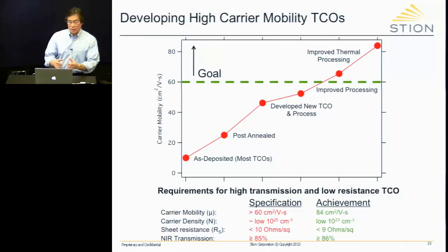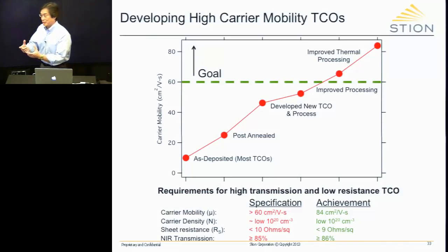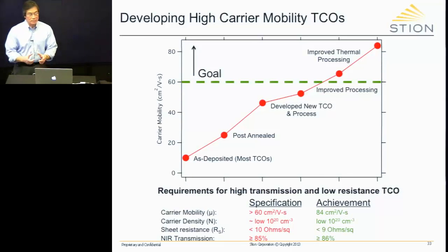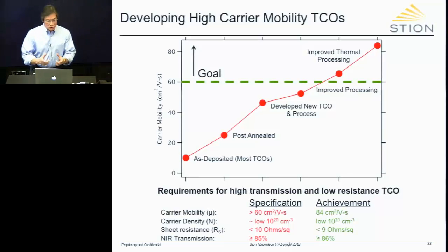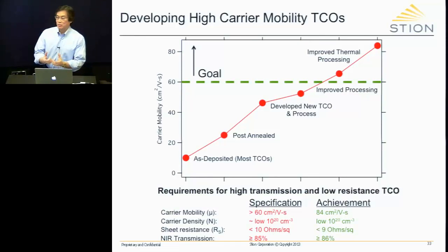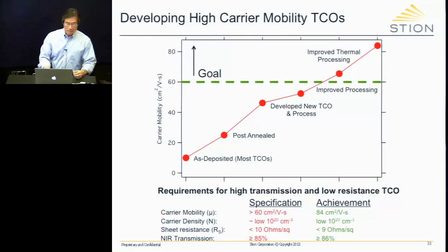If you make a special AZO, in which AZO is aluminum doped zinc oxide or any kind of zinc oxide, if you make a special one in which you make a single crystal, the mobility goes up to about 44. That's the highest I've ever seen. I know because we've done that. Extraordinarily difficult. So what we've done is develop a new type of TCO in processing. We shot it up to about 50, and we increased processing better and better. And now we're at 84 centimeters squared per volt seconds.